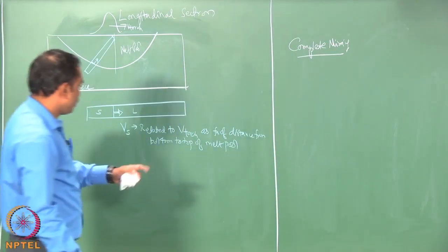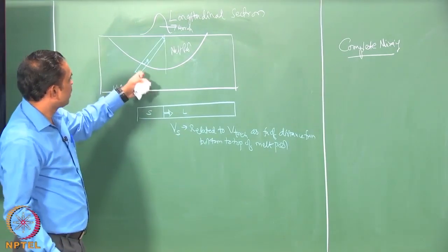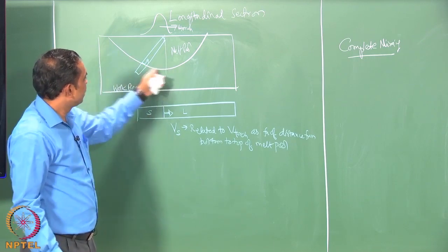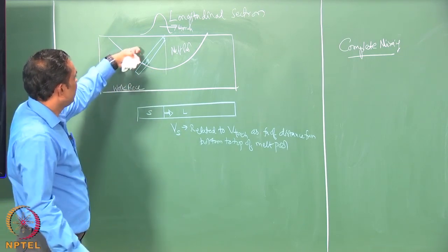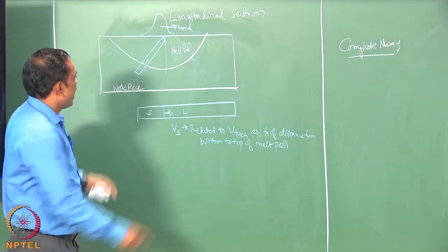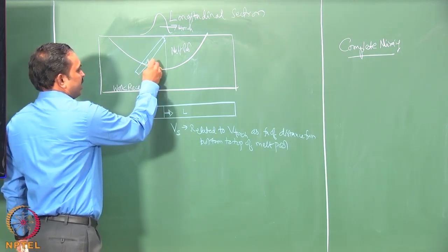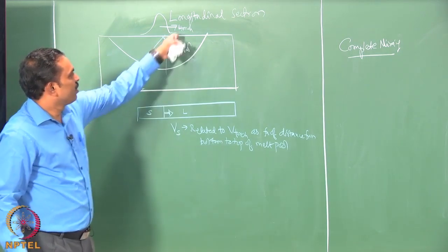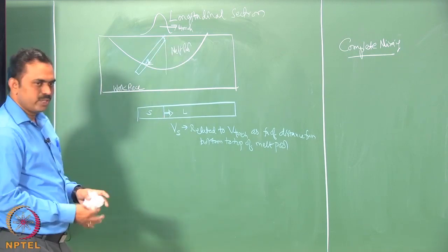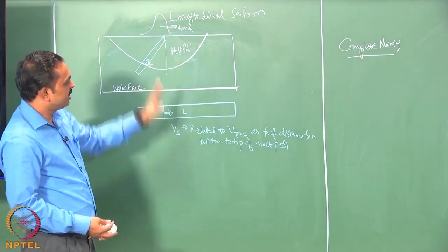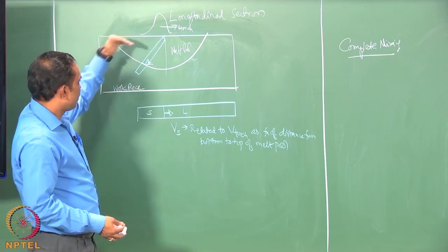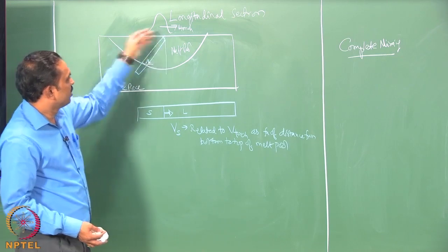Okay. So, before we go there, we can actually just look at the velocity of solidification that we are going to use. That is basically related to the angle that the interface between the melt pool and the workpiece, namely the fusion zone, is going to make with the horizontal, and that angle theta can be used to relate Vs with V torch. Okay. So, at a later point when we come across the velocity here, we should not confuse it with the torch velocity; it is related to the torch velocity, but not the same, and it is not also to be confused with the velocity of the liquid pool within the zone here.